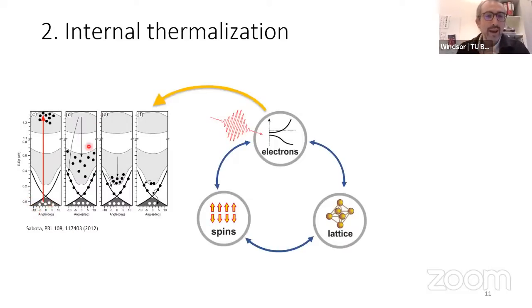a sort of a cartoon of how the electron system evolves following a photoexcitation. We initially have a very excited carrier population up here in nominally unoccupied states, which then cascades back down through a series of scattering events and eventually relaxes to a new thermal state. And with every scattering event here, they lose energy. This energy, of course, is what is transferred to the other degrees of freedom. But this cascade in itself tells us that the heat bath, which we call the electrons or the carriers, is not in equilibrium with itself, and definitely not necessarily in a thermal state.